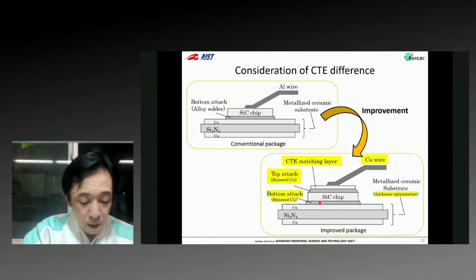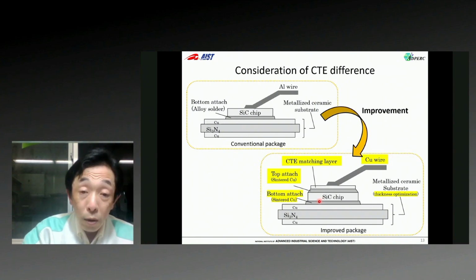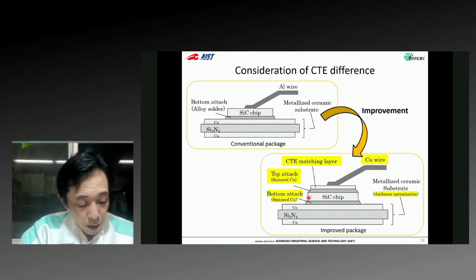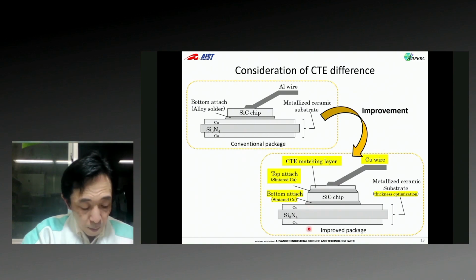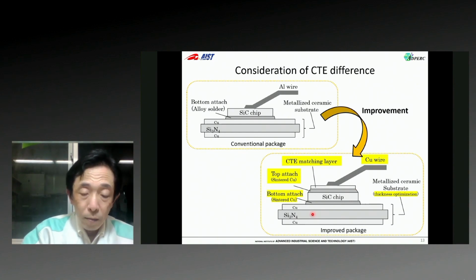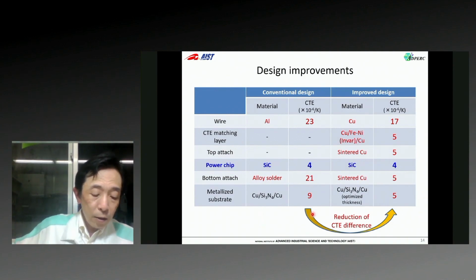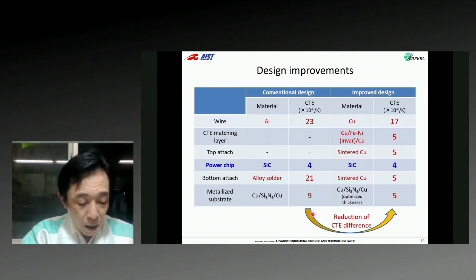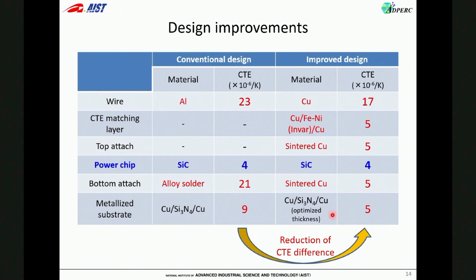Moreover, the bottom attach material is changed to sintered copper because the CTE difference of the SiC chip and the alloy solder is large. The design of the metallized ceramic substrate is also changed. The thickness of copper and silicon nitride are optimized in order to reduce the CTE difference. The result of the material choice is summarized in this table. As shown here, the CTE difference is reduced in the case of the improved design. Therefore, the stress of the contact interface is reduced and the lifetime is greatly improved.